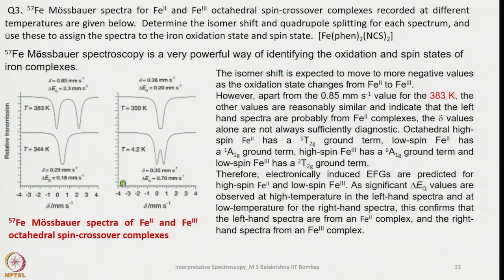So now if you look into the data given for Fe2 and Fe3 octahedral spin crossover complexes, the isomer shift is expected to move to more negative values as the oxidation state changes from Fe2 to Fe3. However, apart from 0.85 millimeters per second, you can see here, and a value for the 383 Kelvin, the other values are reasonably similar and indicate that the left hand spectra are probably from Fe2 complexes. The delta values alone are not always sufficiently diagnostic.